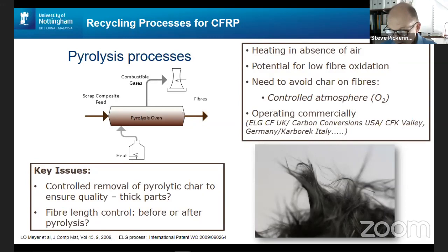a number of carbon fiber recovery operations in the world using pyrolysis technology. And one of the most notable of those is ELG carbon fiber, which is here in the UK. And you'll note from the program of the workshops this week that Fraser Barnes from ELG will be giving a presentation tomorrow. The key issues in pyrolysis processes are being able to remove the pyrolytic char and ensure quality of the recovered carbon fibers, the individual filaments, and also to think about how you're going to control the length of the carbon fibers. You're going to do it by shredding the material before pyrolysis, or have some chopping processes after pyrolysis. So that's pyrolysis processes.